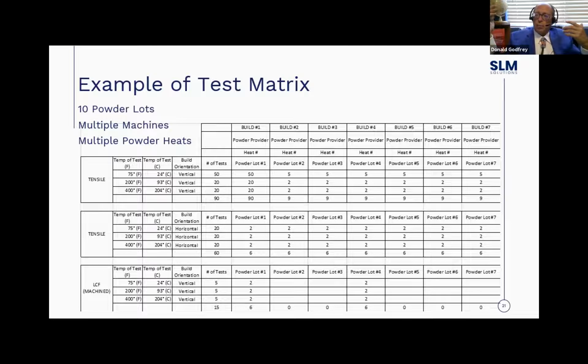So I think I built this just as reference. It's not going to be aluminum, but for nickel, you may test all the way up to 1900 degrees F. But you're not going to test a lot. You may do 20 at that. And what you're trying to do is fill out your curve. Most of your testing is going to be in the 600 to 1300 degree range. With aluminum, it's going to be room temperature to, you might go to 600 degrees, but maybe it depends. So you're going to do tensile as printed.